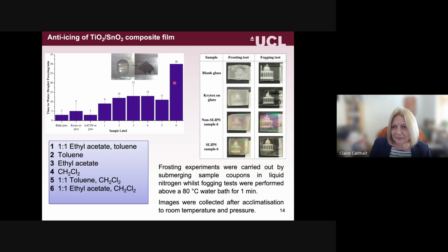We did also look at some frosting and fogging tests, which I'm not going to go into in detail, but essentially that same sample was shown to be the best one, and did show some action as an anti-fogging surface. And a lot of this is down to the fact that you're limiting the areas for nucleation to occur for the ice to form.